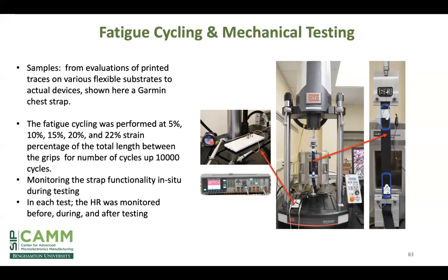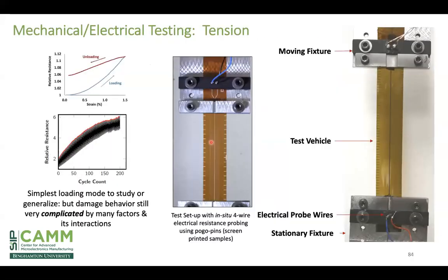where we can in fact see, was the pulse rate still being reproduced in a consistent way, or has the device started to degrade? And ultimately, this is the best way to test systems like this, is literally with an in situ test, an in situ functional test during the actual deformations. Now, of course, we've done this for many more basic and fundamental cases.